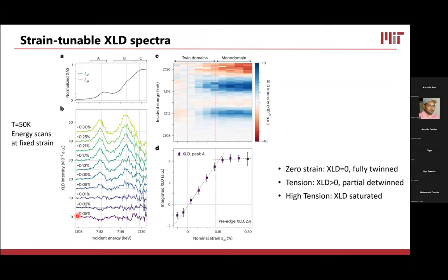And we can see very clearly that when we move from compression to tension, the sign of these peaks will flip. So this A peak feature here starts negative under compression, and it becomes positive under tension. If we plot these line cuts together, we can get this kind of area plot, where this feature right here is our peak A data. So we can see, again, under compression, we have a negative peak here that corresponds to this negative peak, and then it quickly moves into a large positive value that saturates.